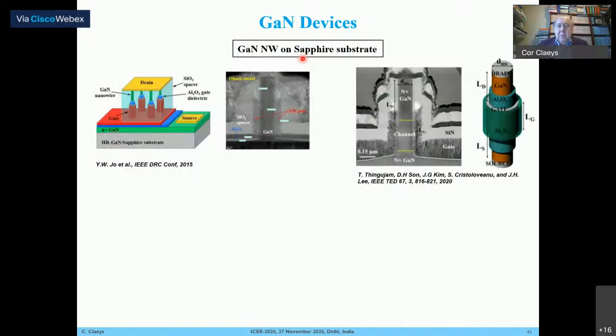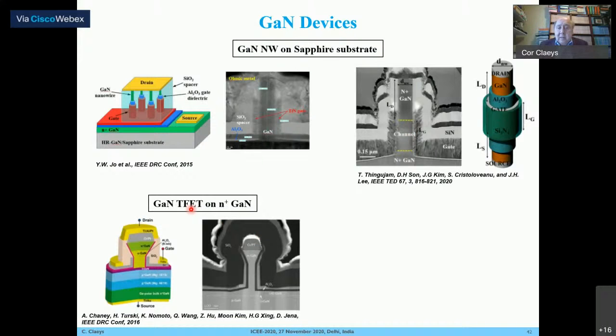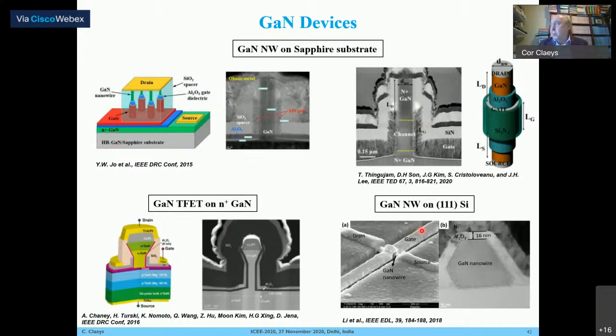And if you look in the literature, you will find already different types of devices that have been fabricated using gallium nitride. In 2015, there was a gallium nitride nanowire. More recently, you see a very, very small area gallium nitride wire. You can make gallium nitride devices on gallium nitride. And of course, you can make gallium nitride nanowires on silicon. And that's what we are really looking at. We want to be able to produce gallium nitride devices, gallium nitride circuits on silicon, because then we can do processing on large area silicon wafers.